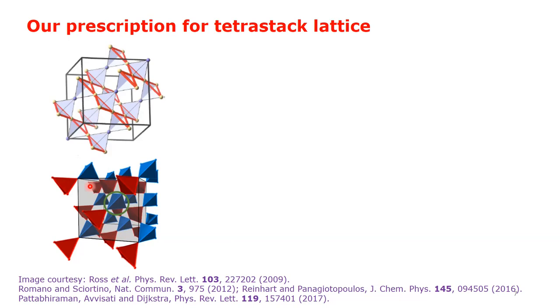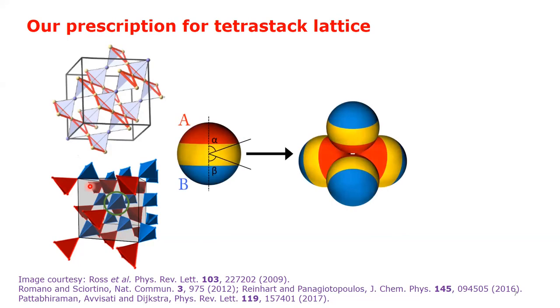Our designer tri-block patchy particles should then have equal size patches on the poles, but a hierarchy of interaction strengths shown by color coding to encode staged assembly pathways.